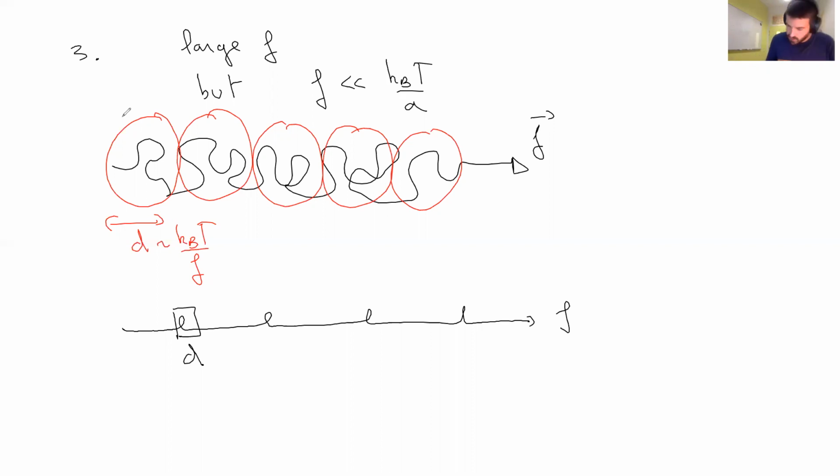Okay. So the very nice argument, I will do the scaling, but it has been calculated more thoroughly by Pincus, is the following: the typical size L will be given by the number of objects, blobs, times the size of one blob, D. And this gives me immediately the force-deformation relation, because in D, there is the force.